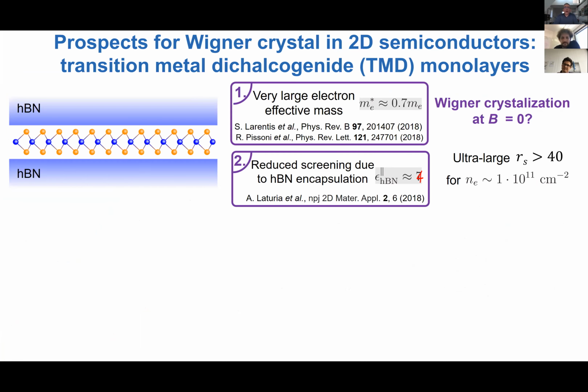I mentioned. Now, the two-dimensional semiconductors, like the transition metal dichalcogenides, provide a new angle here. And again, it's mainly due to the two aspects that I mentioned. The first one is that the effective mass is relatively large, and the dielectric screening, due to the hBN layer surrounding it, is relatively low. And one can even dream about suspending two-dimensional materials and taking the dielectric screening down to unity. Okay, so if you put in the numbers, then at similar densities, one could in principle get rs parameters exceeding 40, making this system potentially an interesting candidate for studying this kind of physics.